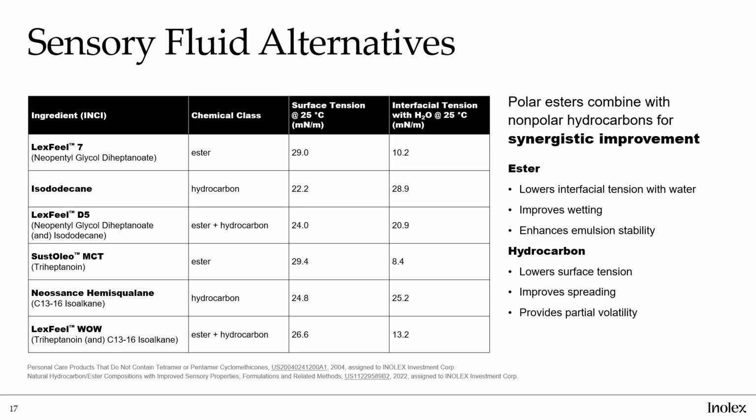This is important when it comes to hair care because esters, even though they're hydrophobic, have more polar characteristics, which makes them more compatible with the hair surface. Hair is, of course, composed of protein. It's hydrophobic, but it does have more polar characteristics. So you have good compatibility between the fluid and the substrate, which results in good wetting or good contact of the fluid on that substrate.